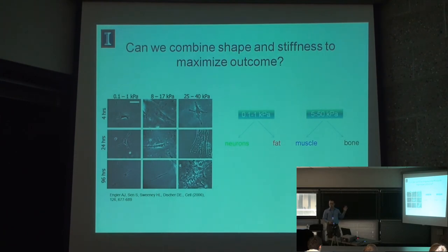And so I just showed you some work where they showed on soft gels you get fat cell differentiation. When we've cultured MSCs on these very soft gels, we see that some cells express beta-3-tubulin, a low percentage of them, while many cells start to accumulate lipid droplets, which appears that they're going towards an adipocyte fat cell fate. And similarly, on stiffer materials, you tend to get a mixture of cells that are expressing markers of muscle and bone.